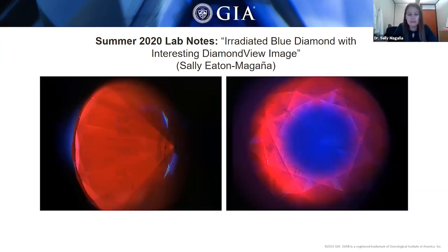The irradiated pavilion shows orange fluorescence due to a high concentration of nitrogen vacancies — NV centers — created by the treatment. Irradiated diamonds are often given low temperature annealing after irradiation to stabilize the defects; however, we generally do not see evidence of NV centers forming from post-irradiation heating. For this one, we do see treatment conditions that created NV-related fluorescence on the pavilion and crown. Meanwhile, the original blue fluorescence of the natural pre-irradiated diamond persists on the table, which was shielded during irradiation. The table experienced a lower radiation dose, fewer NV centers formed as a result, creating an intriguing transition from orange NV fluorescence around the periphery to original blue fluorescence in the middle of the table.